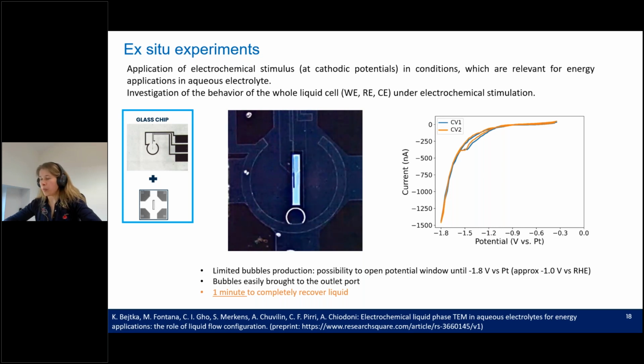We observe the creation of hydrogen at the working electrode, but it must be pointed out, we cannot see it from this video, but I can say it in words. It must be noted that when we are at not very negative potentials, something like -1.1, -1.2 volts, this improved liquid flow configuration inhibits formation of gas bubbles in the working electrode area. The bubble is formed when we reach more negative potentials, where the reaction and the gas products are already quite important. But the gas products are then quite easily removed from the working electrode area as well. And this is because we have improved mass transport around the working electrode area and also within the working electrode area.